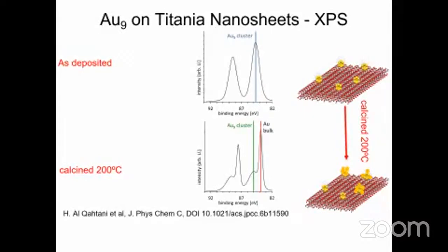We also tried using XPS before and after annealing to show the degree of aggregation. We still have remaining, even after annealing, some isolated Gold 9, but we also have aggregation of Gold 9. But for sure, we don't have any phosphorus left, which means the ligands containing the phosphorus are detached from the Gold 9 nanocluster.